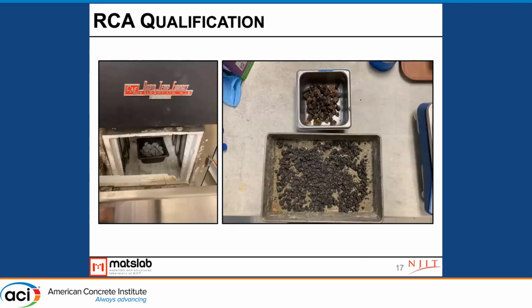So this is the sample going into a muffle furnace, heated up to 500 degrees. When this comes out, it's very, very hot. The pan is completely red. And then when you introduce it into water, there's a lot of activity that happens. And then you're able to take the aggregate out, drain all the water while keeping all of the solids, and then you basically break the mortar off of the natural aggregate, and you wait for it to dry to an SSD condition before you actually weigh the individual components.